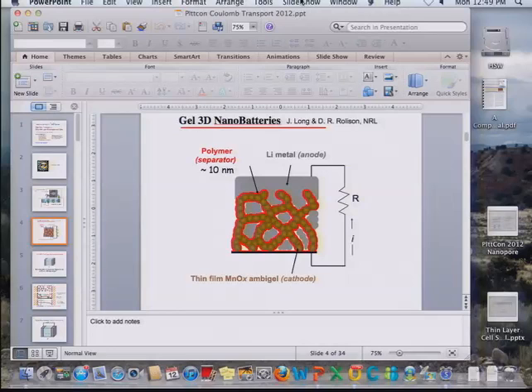And there's an anode that's coated with a very thin polymer film, which acts as the electrolyte, and then you back diffuse lithium metal into it, and you hook up a wire, and it probably burns up still. What does it do? It's like doing molecular electronics. But it's a fantastic idea. Even if it hasn't been perfected, it's a marvelous idea because you get very high energy. If you go through the calculations, very high energy density, but because the electrolyte thickness is very thin, on the order of 10 nanometers or so, these were conformal electrodeposited polymer films, the power stays at a very high level.